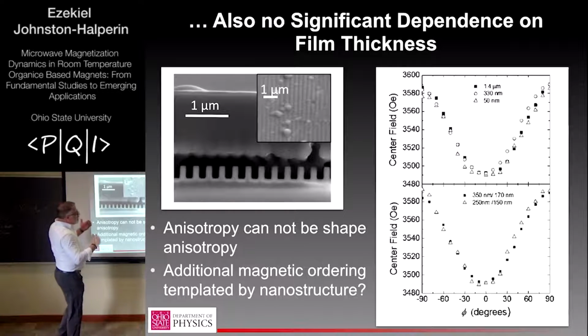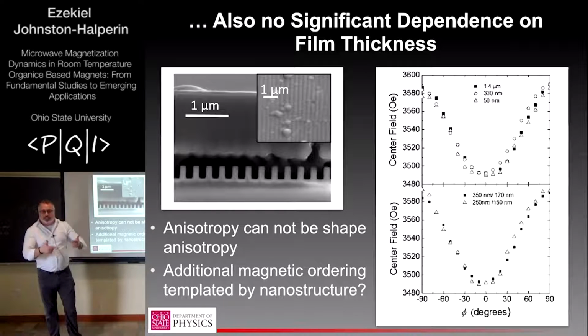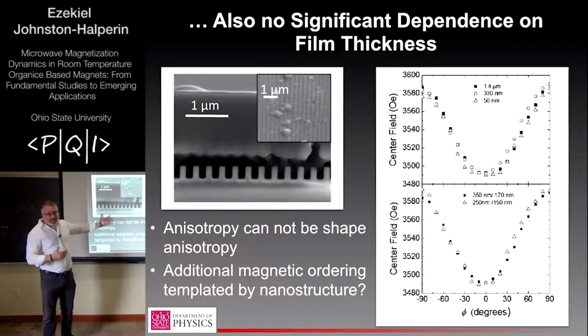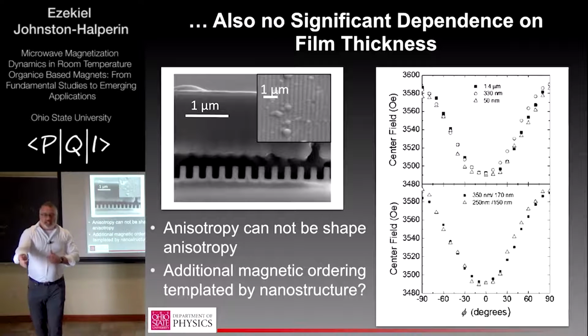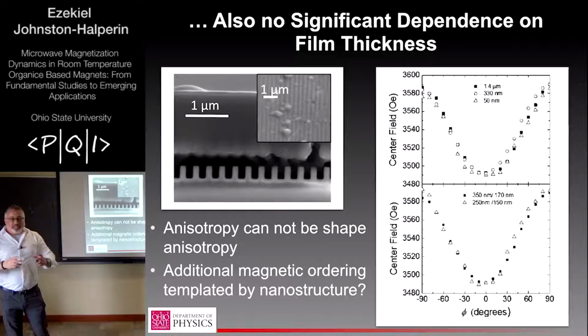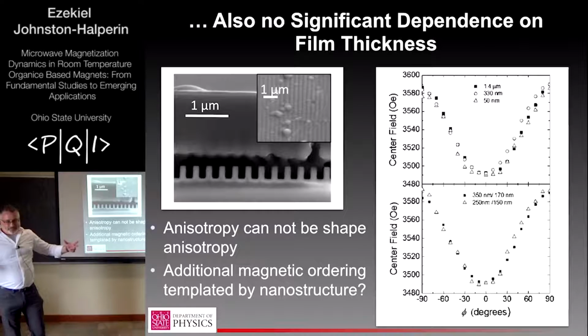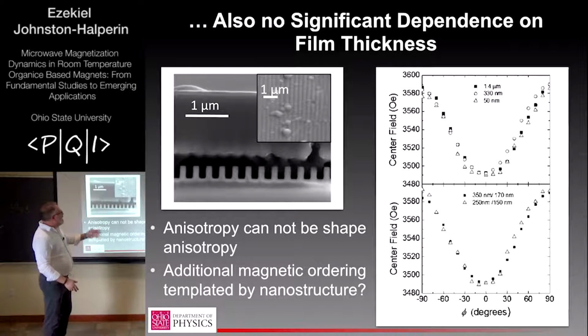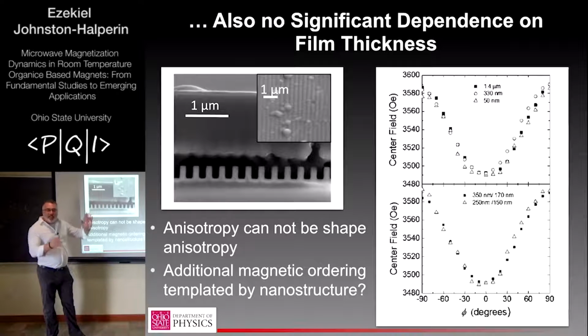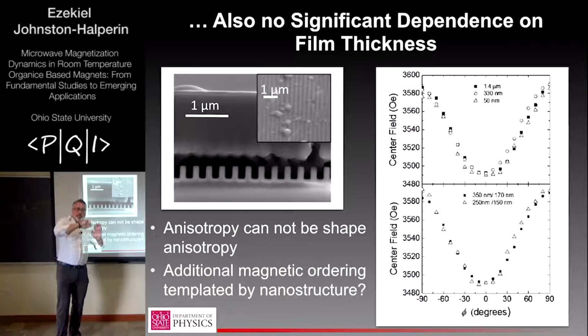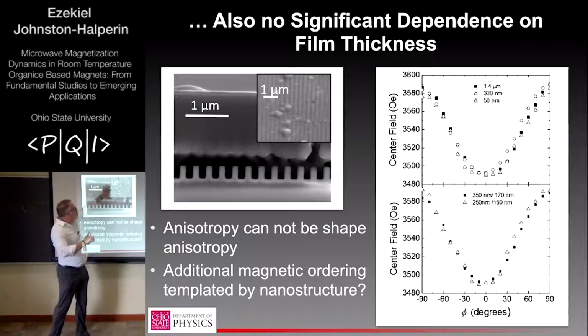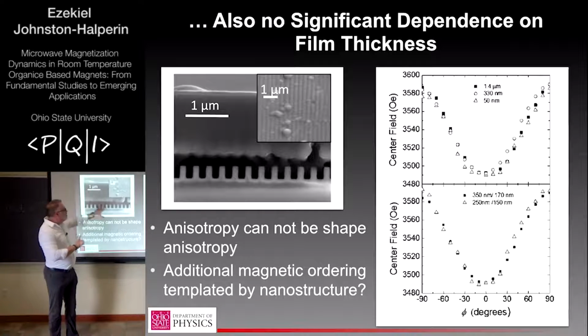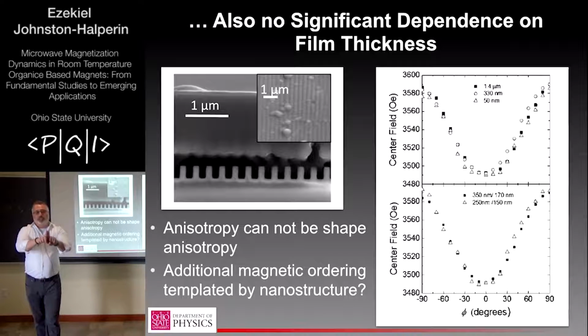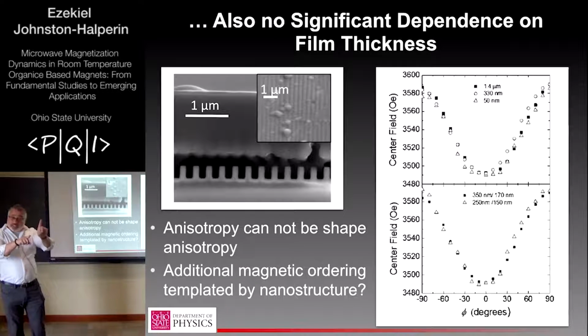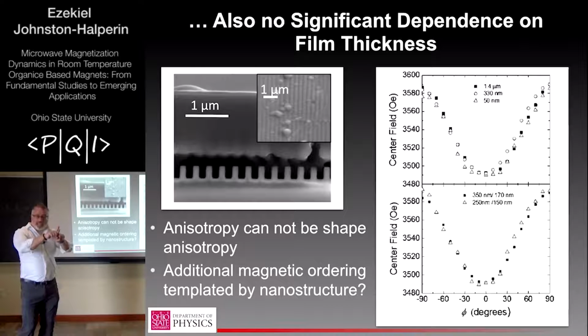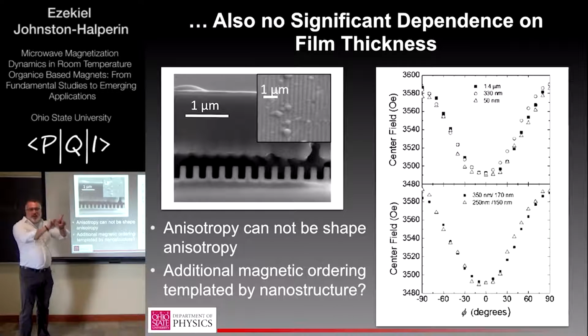Well, I think the problem there is that the signal we look for to see whether that's happening, at least in the magnetic properties, has exactly the same sign as the signal that you get from a larger plate. So you can't decouple. Exactly. It's only by turning it sideways that we rotate this anisotropy by 90 degrees, but we keep the film anisotropy still perpendicular to the bulk substrate. So as we do this, this still remains, but now we get this additional orthogonal component.